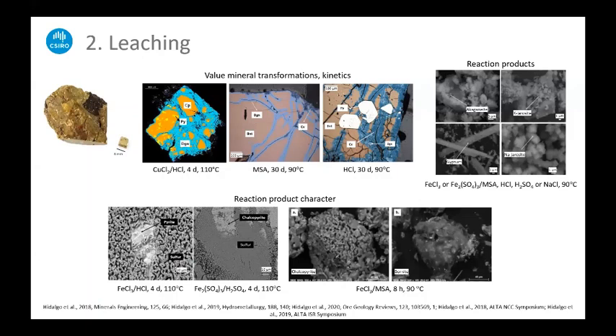And we've looked very much at the reaction product character. So sulfur formation in a chloride versus a sulfate environment, where we found that the product layer that forms on the surface of the mineral tends to be more porous and therefore allows fluid access to the mineral surface. And this has been seen previously in other literature.